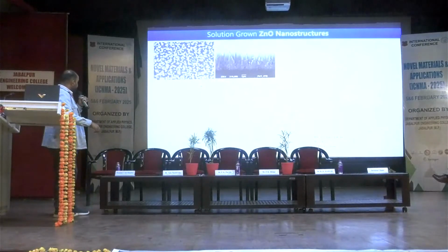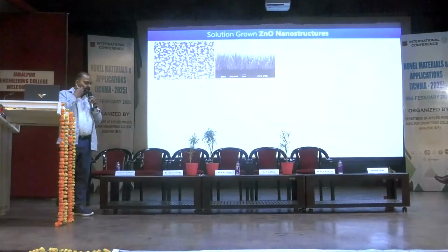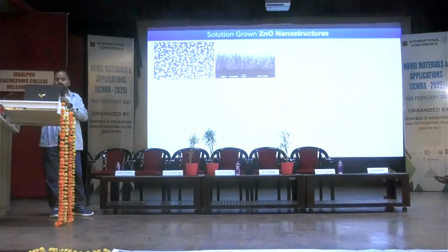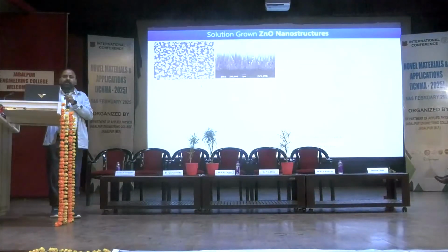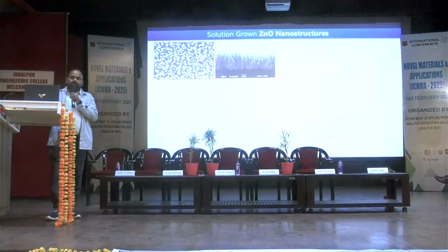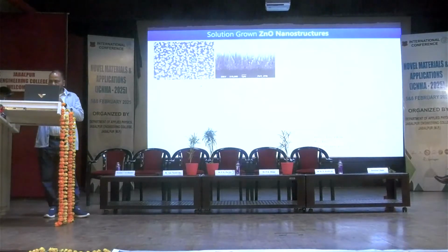And we have used this material related to the substrate. When you make the electrode, if you are making a powder electrode, then stability and uniformity are one issue. So we thought, why not just grow the structure on the substrate, and use it as an electrode. So we used the zinc oxide system, and we adopted several strategies.